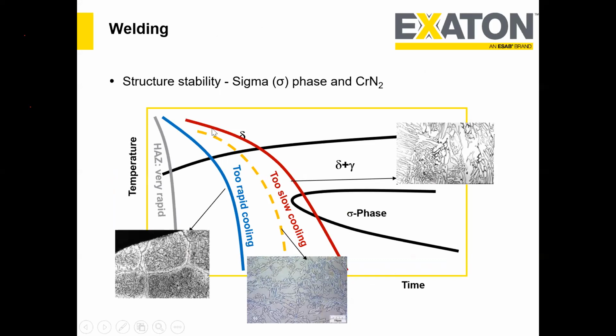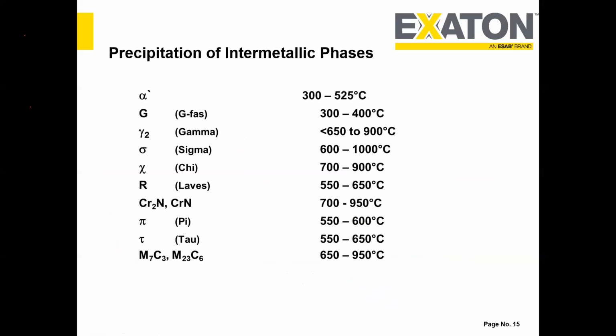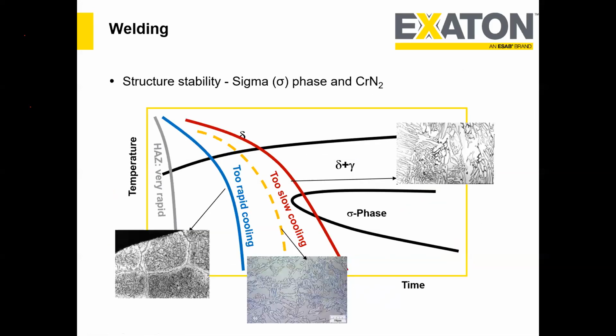When we're talking about welding, which is the most critical part, this is basically the most desired zone. If you remember, on some previous slides I mentioned that the final structure not only depends on the alloy elements, it also depends on the cooling rate. As I explained, these intermetallic phases are a function of temperature and time. When we solidify, if the cooling rate is slow, there's a high potential that my liquid weld metal will stay in the critical temperature zone, let's say 1000 degrees centigrade to 600, 500, 400, and slowly it will go to room temperature.